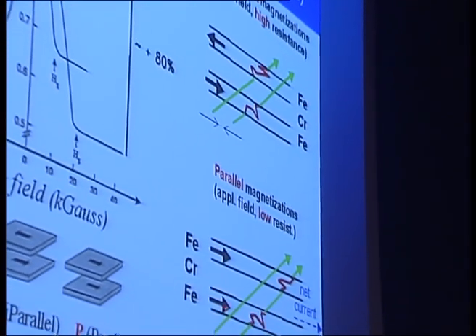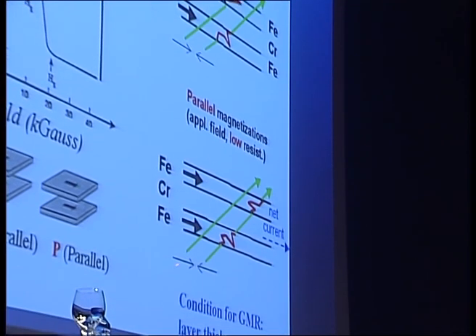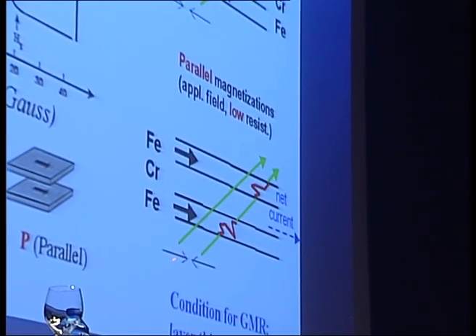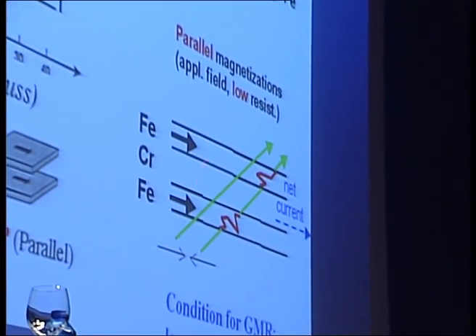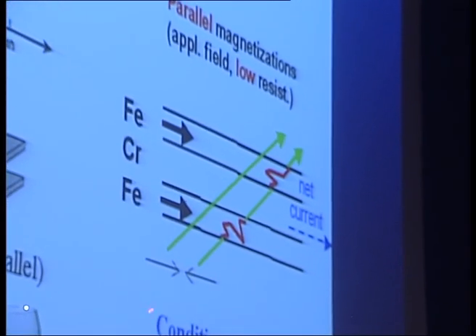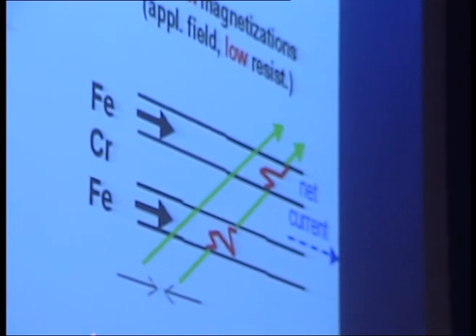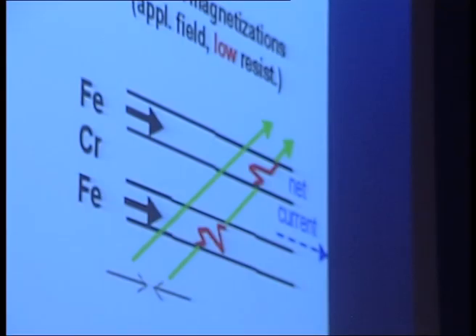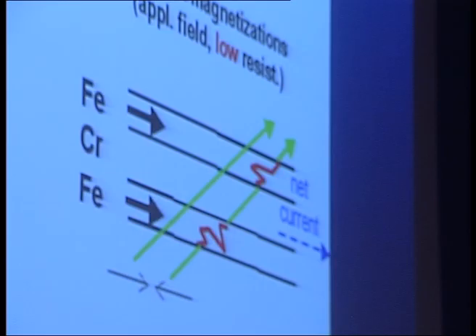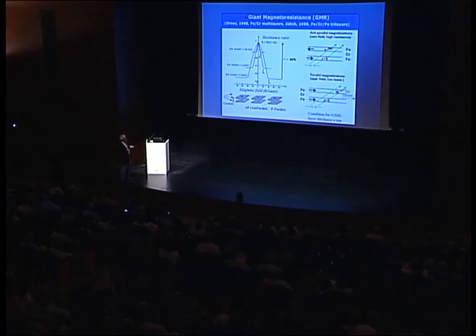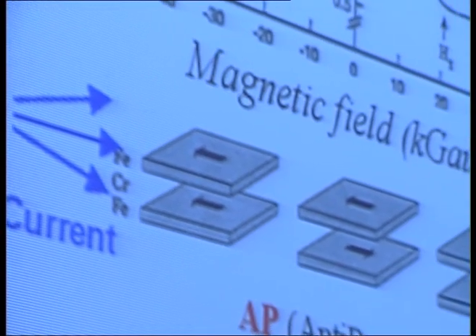When all the magnetizations are parallel, one of the spin directions can go through easily through all the magnetic layers, and due to this shorting of the current by the channel, the resistivity is low. On the contrary, in the anti-parallel configuration, the electrons are slowed down every second layer in both channels, and the resistivity is high. In fact, even if the current is along the layer, there is a random velocity of the electron, so that finally the mean orientation is oblique.